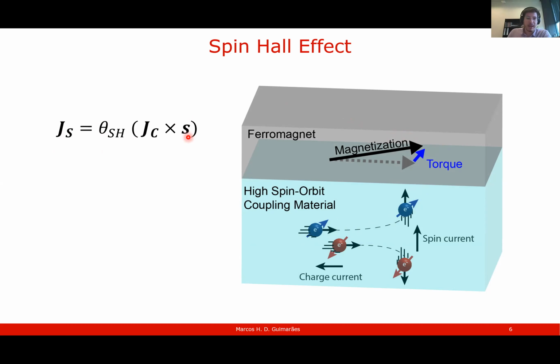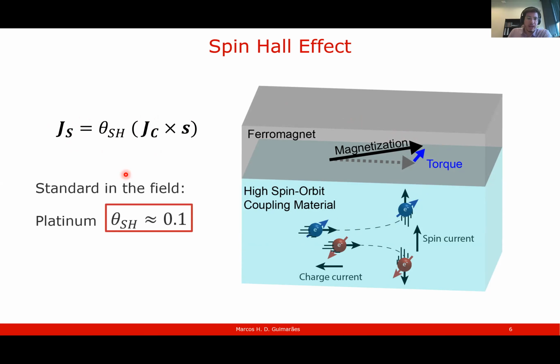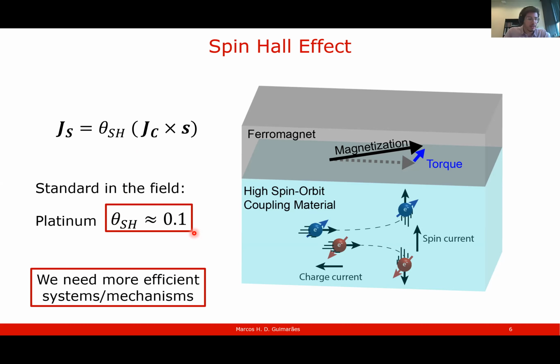And we can quantify this, so we can write down that the spin current density Js equals the spin Hall angle, which is the efficiency, times the charge current density. The standard in the field now, and also what's being used to develop the SOT MRAMs, is platinum. And platinum has an efficiency of about 10%, which is pretty low. So there has been a drive in the field now to find systems which show more efficient conversion from a charge current into a spin torque, and also different mechanisms. Because one thing that the spin Hall effect doesn't give you is a very efficient way to switch out-of-plane magnetization, which is used in modern magnetic technology.